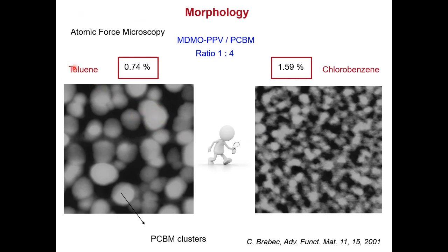And for instance, here you see that we have taken the same materials with the same ratio in solution, and we have deposited a film, but in toluene or in chlorobenzene, so just changing the solvent. Here in toluene, you have a segregation, but you have big clusters. And so this is not the nanostructuration that we are expecting. In chlorobenzene, you see that there is a much better mixing of the two components, and as a result, the efficiency of the device is much better. So a bilayer is very easy to make, but you lose a lot of excitation, and it's very challenging, but this is what we have to do nowadays, is to find the right condition to have this kind of very homogeneous morphology.